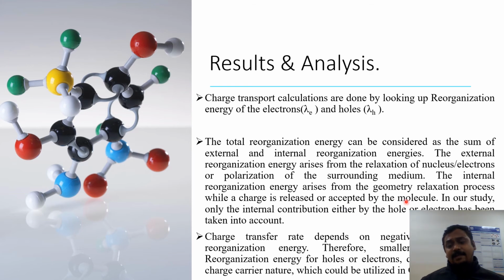Similarly, we have the external reorganization energy, which comes from the polarization of the solvent molecules or the surrounding medium, and how it affects our molecules. It is tough to calculate the external part, but it is easy to calculate the internal reorganization energy. So we have calculated that, and mostly researchers do that.